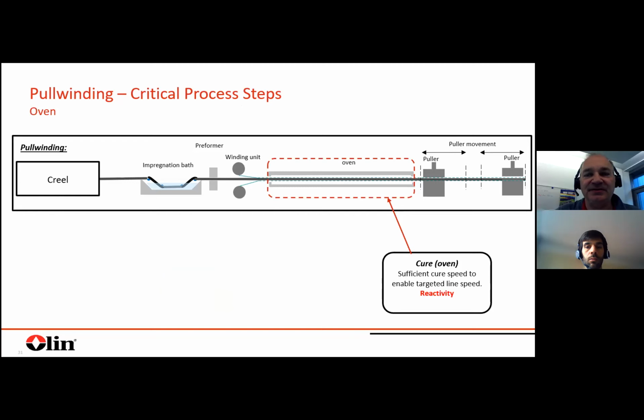So the last critical step is the cure itself. From a process robustness or quality point of view, it's really the cure speed and the degree of cure. So how well cured is your part. This is really the criterion here. And this is for sure related to the reactivity of your system. And this is also, I would say, the reason why the impregnation is a limiting factor. In the front, you need less reactivity to ensure a good and long pot life. At the end of your line, you would like to have a high reactivity to speed up or to shorten your oven, whatever is your preference. But there's a bit of a fight between these two requirements.